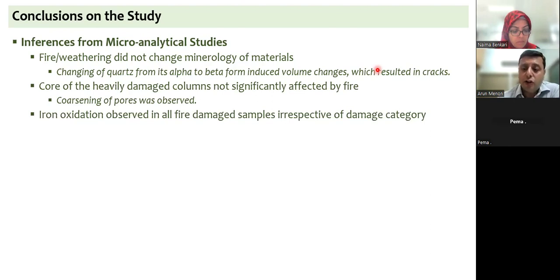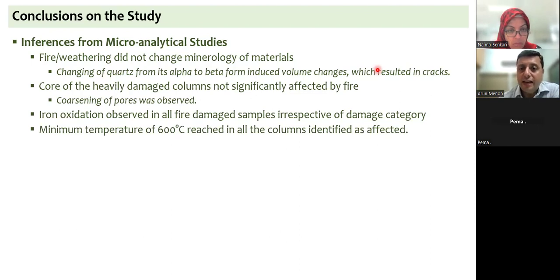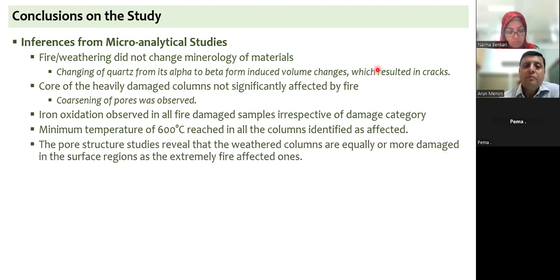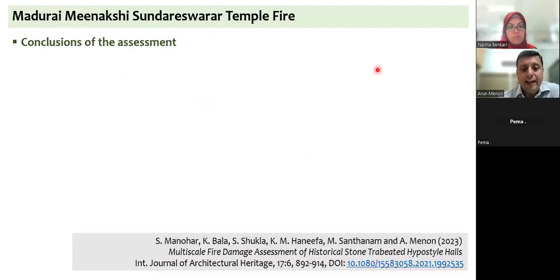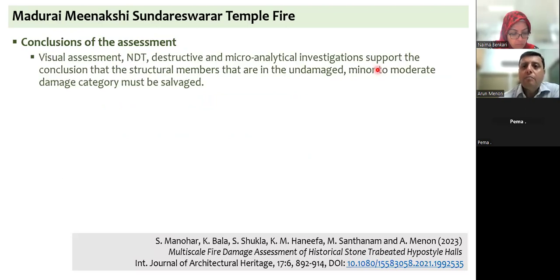But we had seen oxidation of iron, as I said, ferrous to ferric oxide. We had seen oxidation of the iron in all the fire damage samples, irrespective of the damage category, meaning that a minimum temperature of 600 degrees was reached in all the columns in the site. And as I said, we were also examining the weathered columns with the extreme fire-affected columns. The weathered columns and the fire-affected columns are actually comparable in terms of their damage. So final conclusion, maybe I will stop and then close this discussion as I begin in the next.